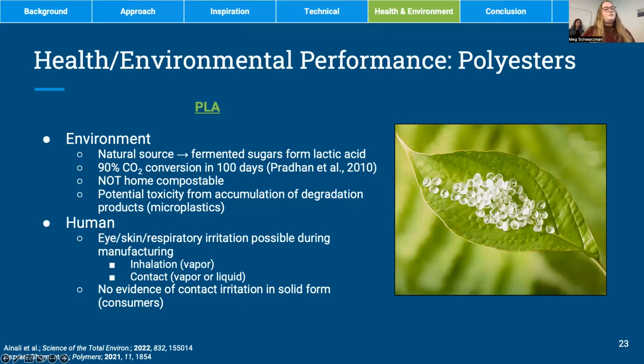And then another red flag is that this is a bio-based polymer, but the degradation process still results in microplastics because it's a bio-based plastic. This is something that really hasn't been studied well, but is getting a lot of attention. In fact, the number of studies focused on PLA microplastics in 2021 was over 5-fold what it was in 2019. So it's gaining a lot of attention, but that being said, there's still a lot unknown about exactly how persistent those byproducts of biodegradation are in the environment. So it is something to be aware of.